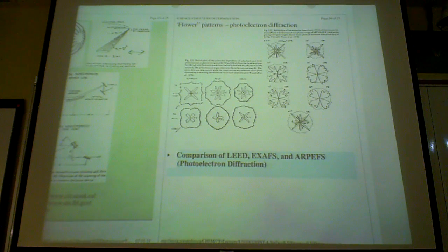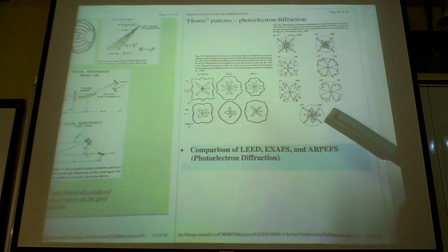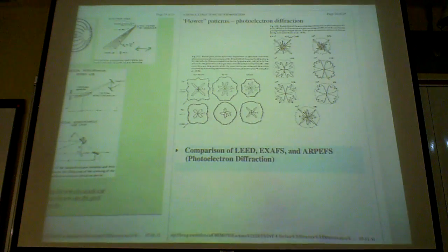Instead of calculating the energy curve, the diffraction pattern, the chi curve, you can calculate the angular distribution just the same way by assuming a geometry of your surface, and then you can use some theory and calculate and compare this angular distribution at a fixed photon energy, therefore a fixed wavelength.